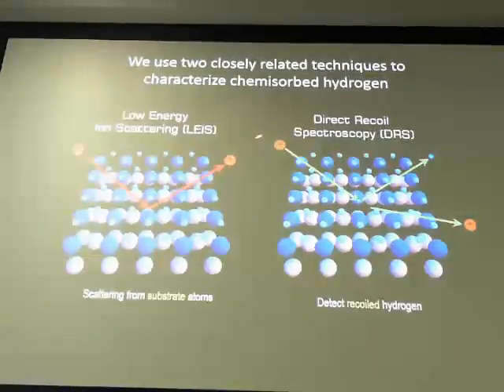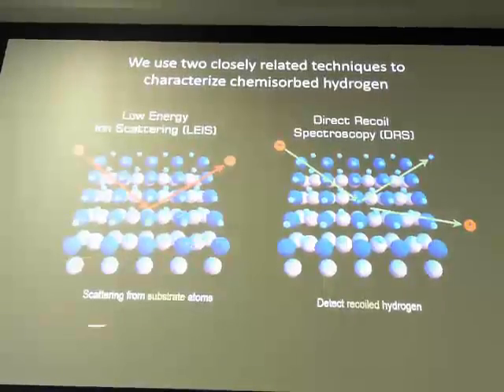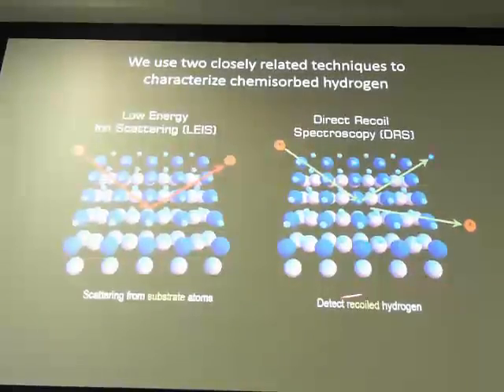And so you look at the scattered ions to obtain information about the substrate atoms, and then you can look at recoiled hydrogen to get information about the structure of the hydrogen that is chemisorbed on the surface. So we have a unique instrument at Sandia that is capable of looking at this in detail. And we noticed that studies on beryllium crystals are quite rare.